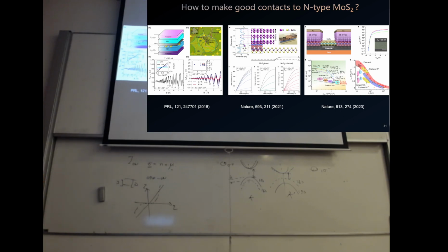This is a PRL paper from Ensslin's group in Switzerland. What they did was try to put MoS2 directly on top of platinum contacts. So they put platinum first, then use AFM to clean it, and transfer a layer of MoS2 on top. In this way, they can have high-quality samples. They have seen some kind of SdH oscillations. Not very bad. But the reproducibility, I'm not sure, because the publications using this method are very limited.